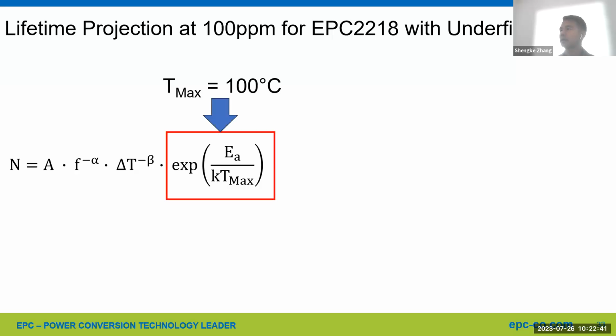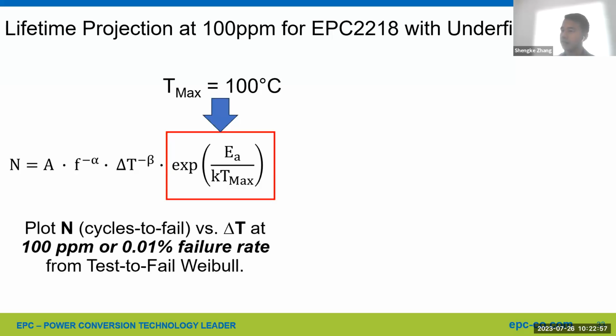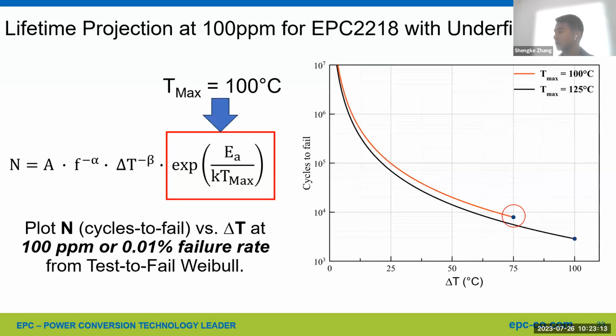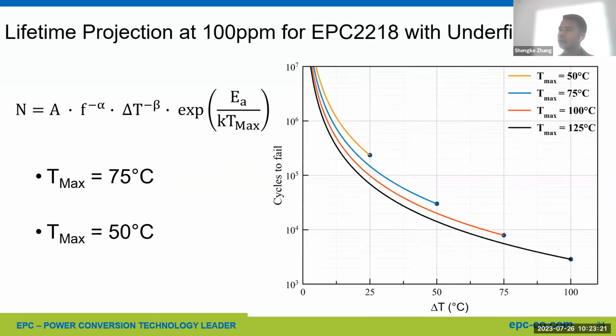Now let's assume Tmax is only 100C, which is less than the previous case. Based on the understanding of the underlying failure mechanism, we ought to have a slightly longer lifetime, right? So now let's plot N as a function of delta T again by assuming Tmax is 100 Celsius, 25 degrees less than the previous slide, at 100 ppm, 0.01% failure rate. Here's the result, where we see slightly improved lifetime compared to Tmax of 125C. Now we add Tmax of 75C and Tmax of 50 Celsius, and plot them on the same plot as shown on the right. As you can see, it makes sense. As Tmax decreases, we get more and more lifetime.